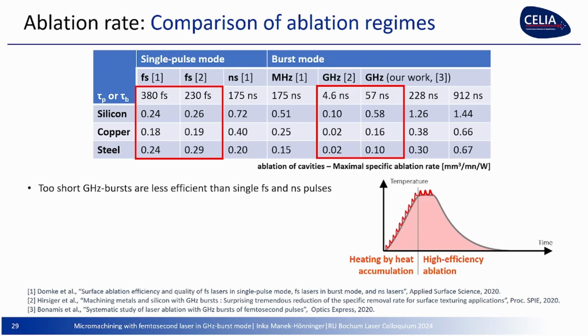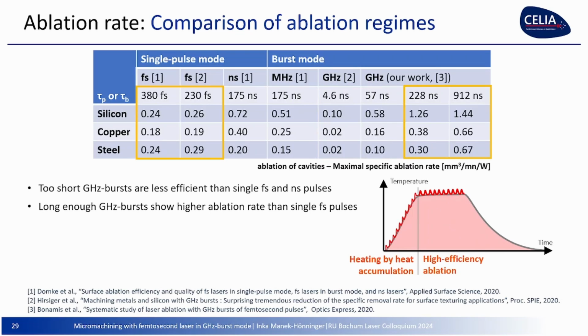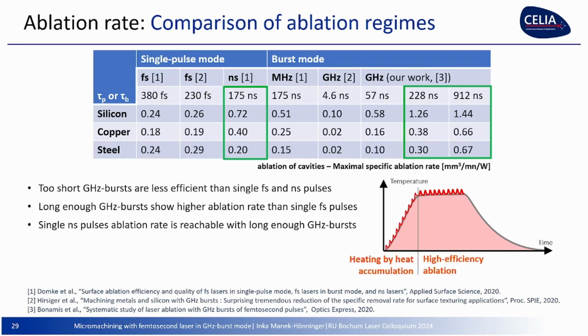So when the burst is too short, it's not interesting because you're just heating up, but you're not ablating. When you go to longer bursts, then you can profit and you can ablate, and higher ablation rates can be achieved, even exceeding the one of single pulses. And with long enough bursts, even rates of nanoseconds can be reached, and there's, however, better quality than with them. So this is the good point here.